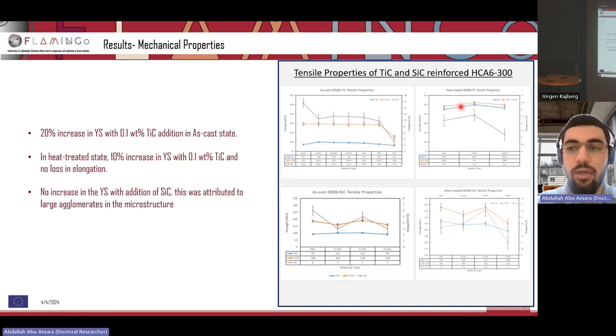So instead of a 20% increase in yield strength with 0.1, we were only able to achieve a 10% increase with the addition of 0.1 titanium carbide, which again is still quite significant considering that the alloy is optimized. But the reason why this increase was reduced is because other strengthening mechanisms which are inherently present in the alloy are taking over and outweighing the nanoparticles that we added. So, for example, the precipitates forming and the strain hardening effect. But nonetheless, we still managed to achieve a 10% increase in the yield strength with the addition of 0.1 weight% titanium carbide.